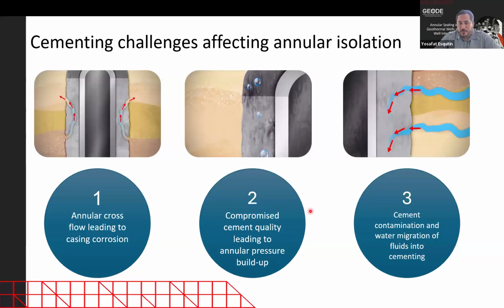Compromised cement quality. So again, especially when you're doing multiple frac jobs and stimulations, the cement gets shattered, and then you start having this microannuli and channels that gas can migrate through to surface, leading to annular pressure buildup or sustained casing pressure on surface. And finally, cement contamination from either water migration or gas migration into the cement while it's curing. And when this happens, once the cement is cured, you still have those challenges presented in the previous slide. So it's very important that when we are using cement for well integrity purposes, we select the right properties of the cement for the application, and often combining it with other technologies brings a lot of benefits.